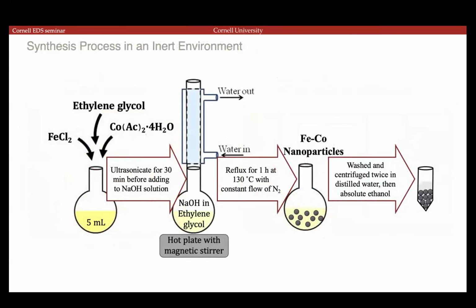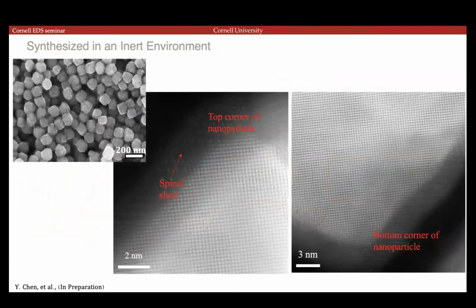So my student Yulan Chen synthesized iron cobalt nanoparticles and developed a process to get a very good dispersion, so uniform distribution of these nanoparticles in size, and also a crystalline nature to them. So they have a cubic structure in the end once they're synthesized, and you can see that the structure of the nanocube is well ordered. Once you remove the cube from the synthesis, then it oxidizes at the surface. So we do confirm that there's a spinel shell, but the main part of the nanoparticle is purely iron cobalt.